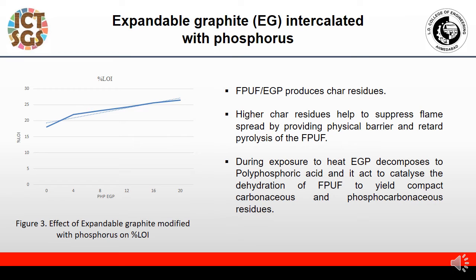The third one is expandable graphite intercalated with phosphorus. Here the effect of the EG intercalated with phosphorus on the polyurethane foam is shown. The percentage LOI in the graph shows an increase with the increase of the expandable graphite intercalated with phosphorus. This combination produces charred residues, which help to suppress the flame spread by providing a physical barrier and retard the pyrolysis of the flexible polyurethane foam.